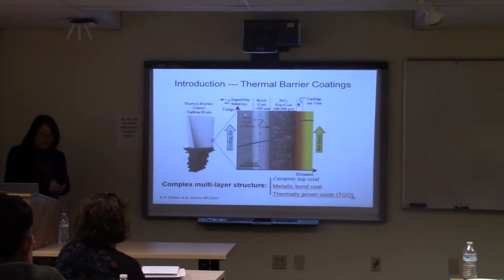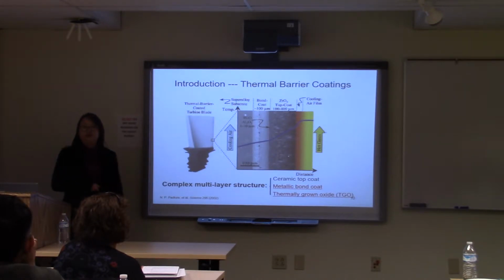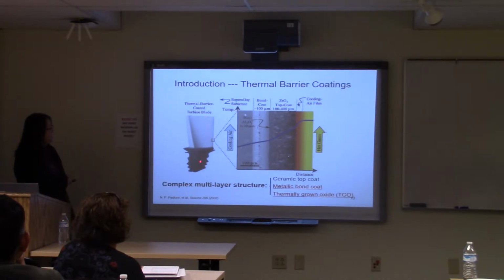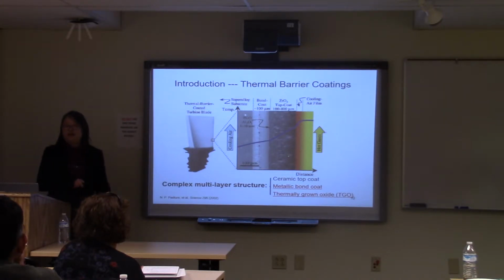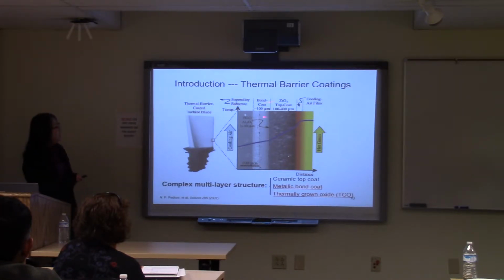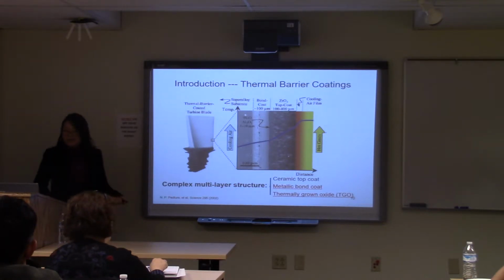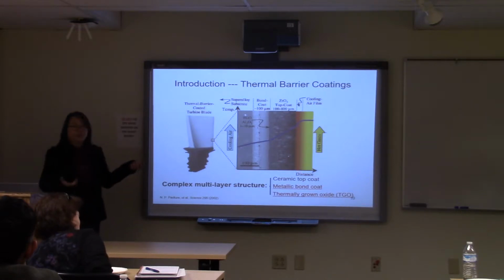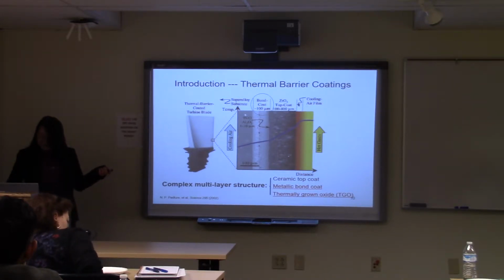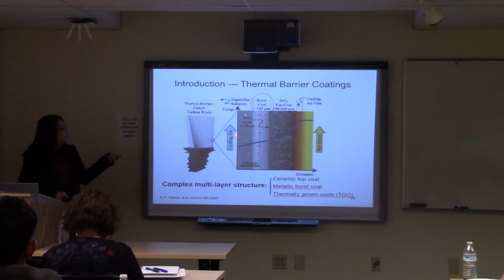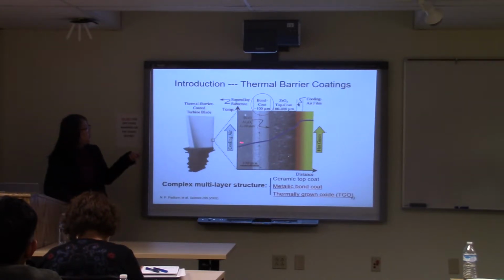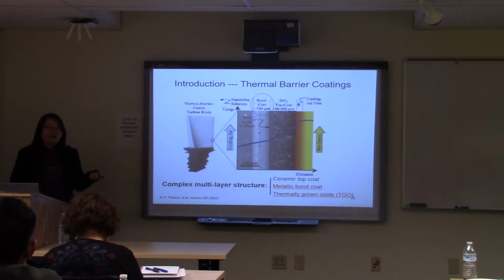Thermal barrier coatings are very commonly used to protect gas turbine blades from a very harsh environment, with very long thermal exposure at high temperature, usually about 1000 degrees C. People apply these multilayer thermal barrier coatings, which include a ceramic layer that provides thermal insulation, and a metallic bond coat in between to provide adherence between the substrate and the top coat and reduce the thermal expansion mismatch.